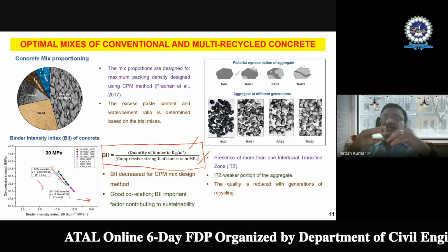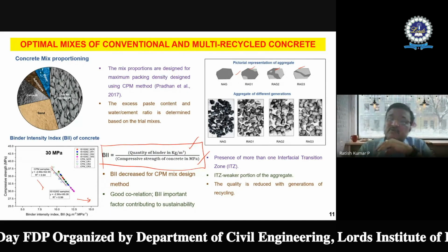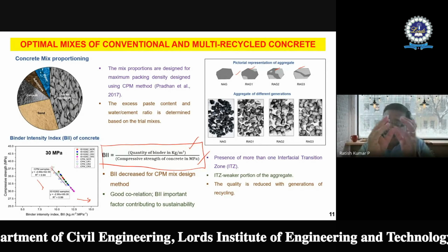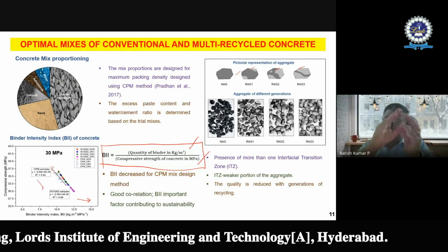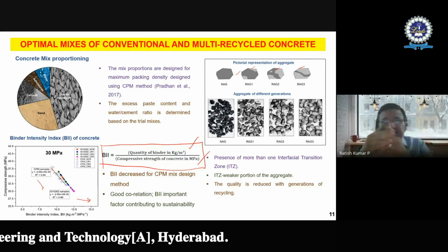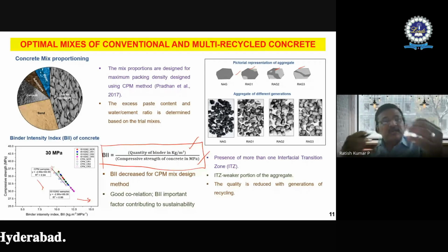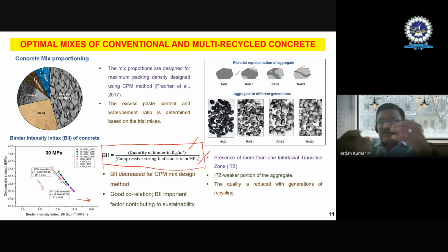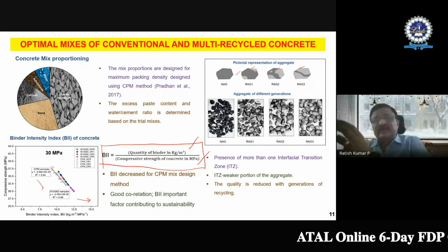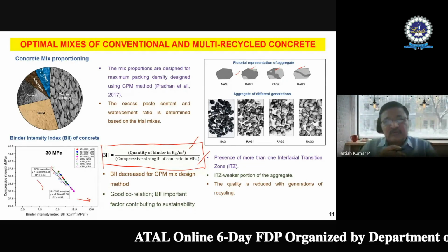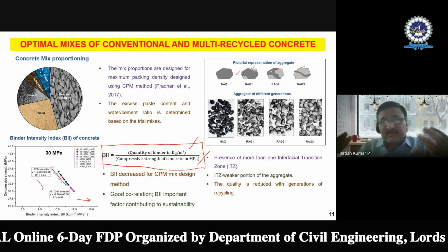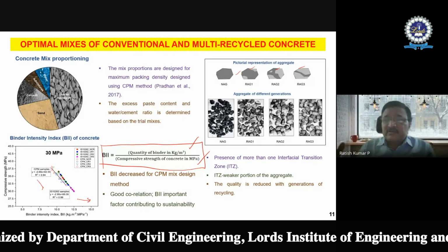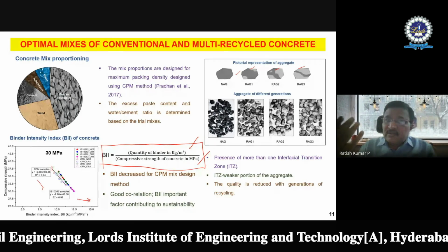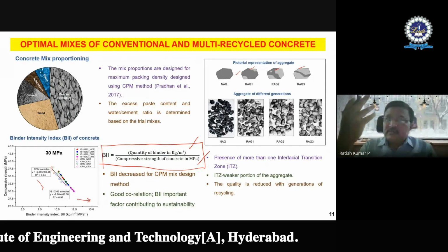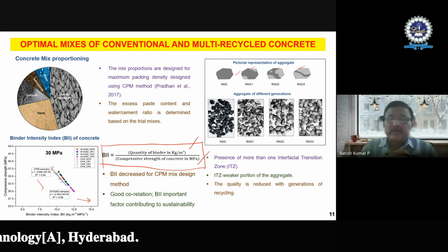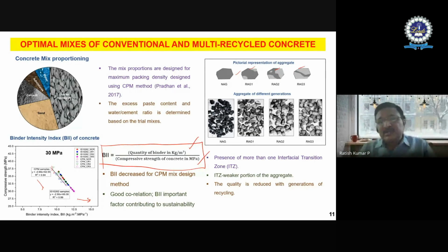Because the interfacial transition zone, which is in between the aggregate as well as the paste phase, is obviously a weak phase, and that is more so because you're going to get multiple interfacial transition zones as you go towards the different generations of recycled aggregate. So I'm aware of that. We know that, and we are trying to go for a subtle level of crushing, so that not much embodied energy is going into that. So all that I'm aware of, all that is taken into account.